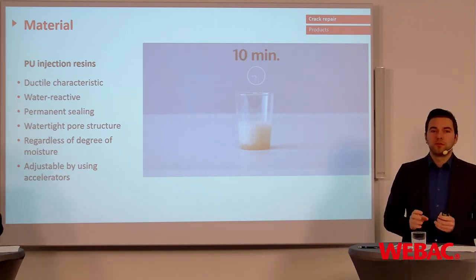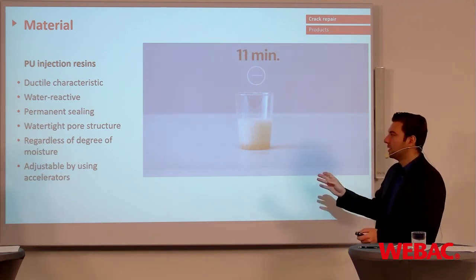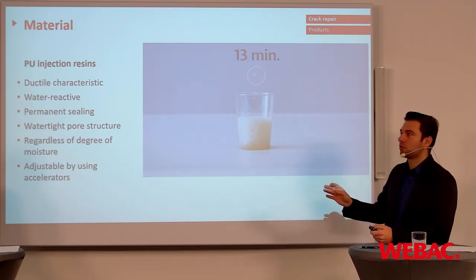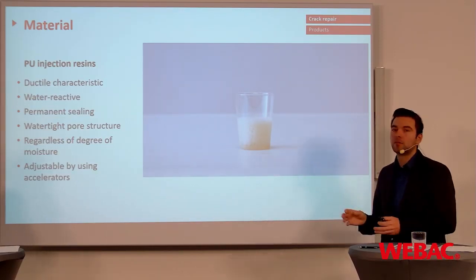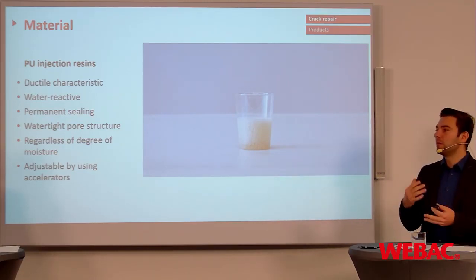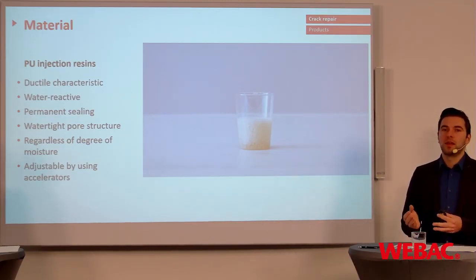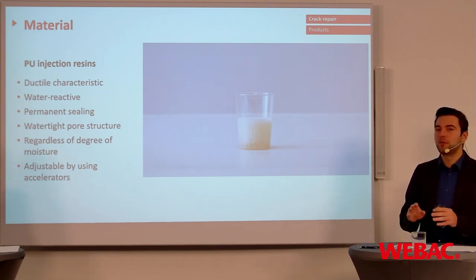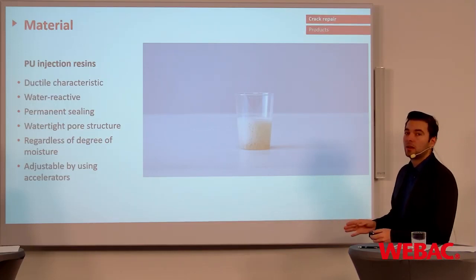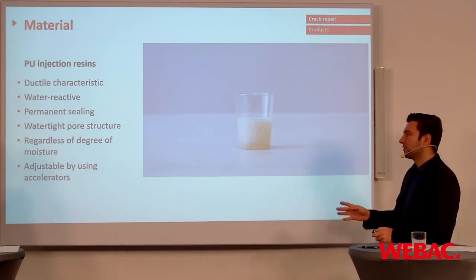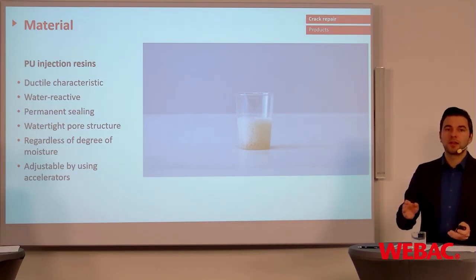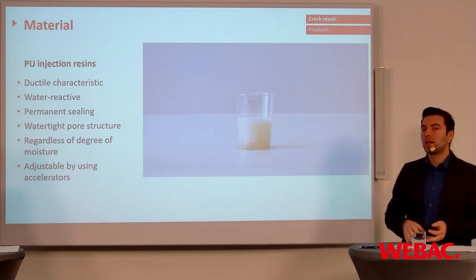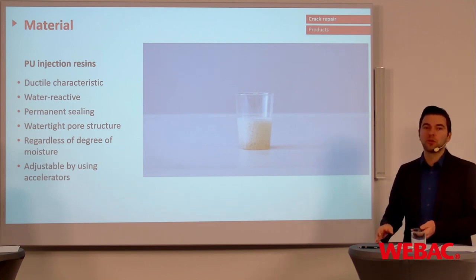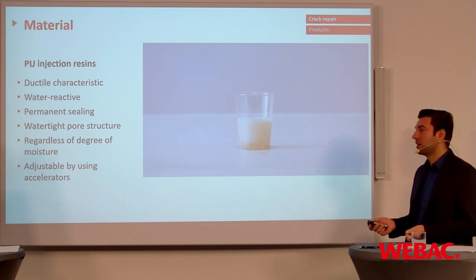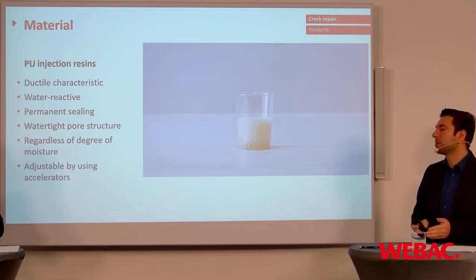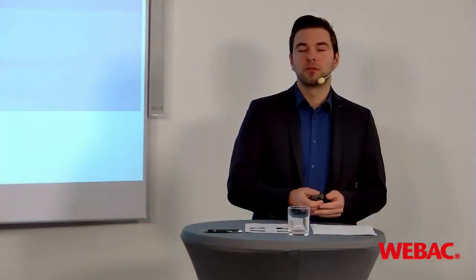This material and also the foam structure is designed for a permanent sealing because they have a watertight pore structure. So if you would put the foam underneath the microscope, you can see that there are not too many bubbles, and you have a watertight structure. So if you're injecting a PU resin like this, the crack is filled and you have a long-lasting sealing. As mentioned before, regardless of the degree of moisture, so it's dry, damp or wet, and for sure you can adjust the reaction time by using accelerators. Especially now in winter times, there might be the need to speed up the reaction.